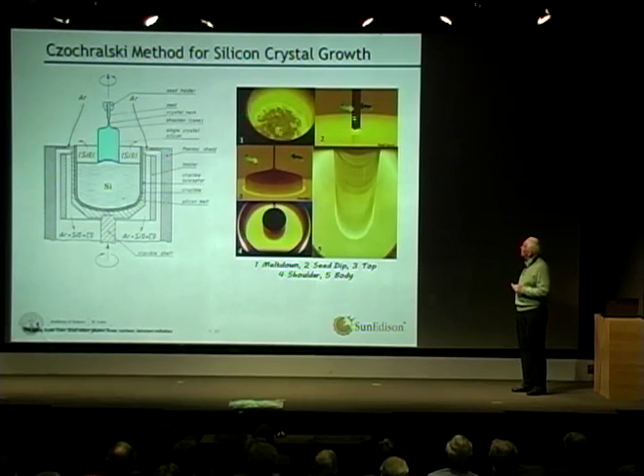And then we dip a seed crystal into the melt. Once everything's molten and stabilized, we dip a seed crystal in. And we start to pull a crystal out. And we start by growing a very thin neck. And we do this so we can avoid dislocations. As this seed hits the melt, there's a thermal shock. And it creates some defects in the end of the crystal. So by growing this long neck, the defects move out of the crystal and leave it dislocation free.